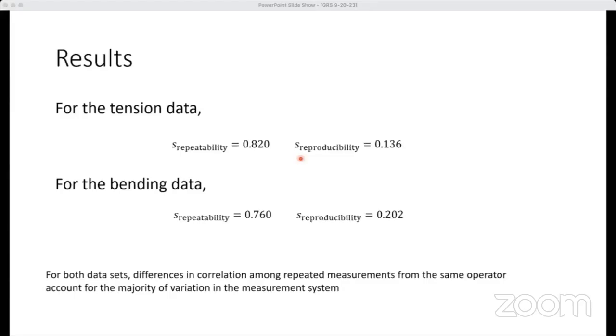And that, to us, is a good thing, that this reproducibility aspect is so low. It's telling us that if somebody else from maybe some different lab images a sample in the same way that we've imaged ours with the 6 overlapping images and everything like that, they should expect similar results in terms of this classification problem that we posed before. And the same sort of thing is true for the bending data. The only difference is this reproducibility bit actually takes up quite a bit more of that measurement process variation.